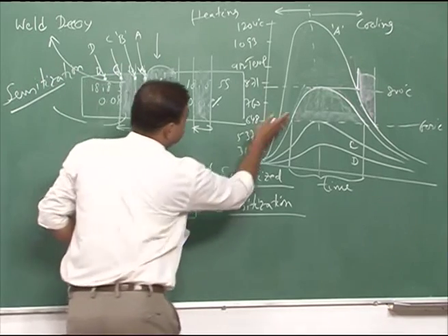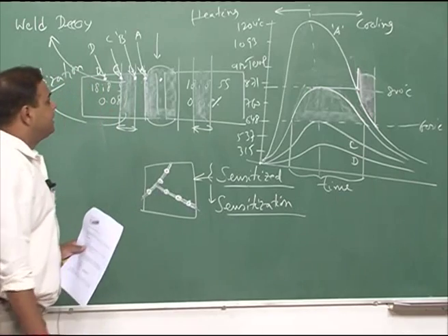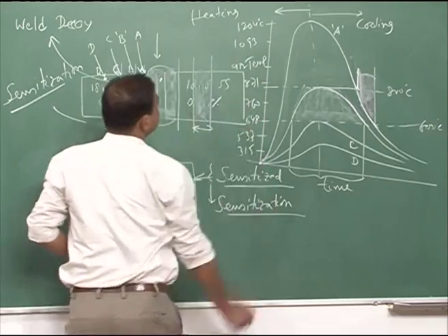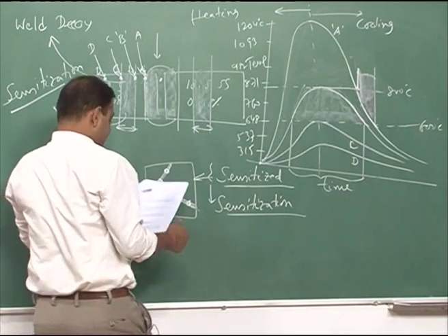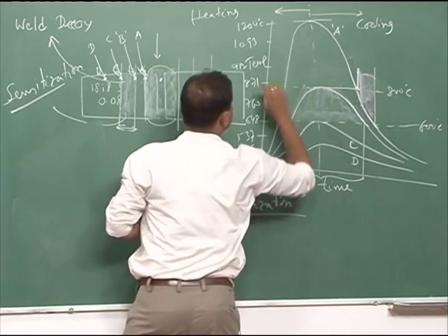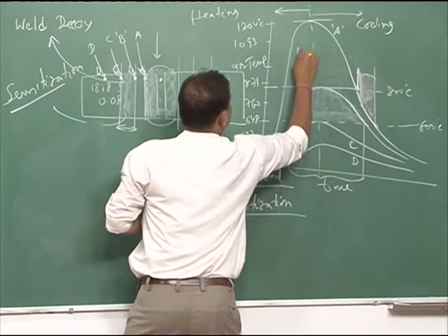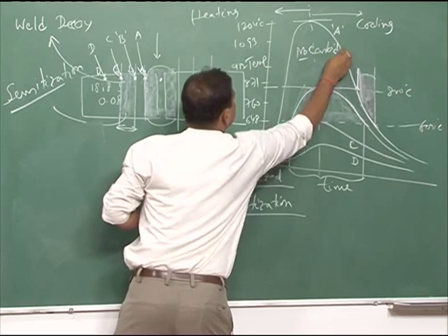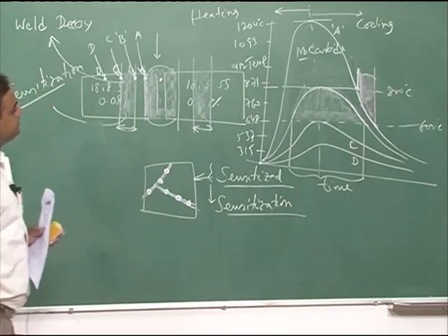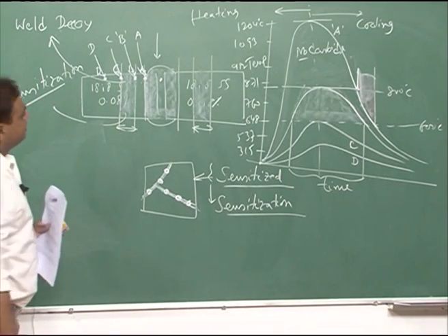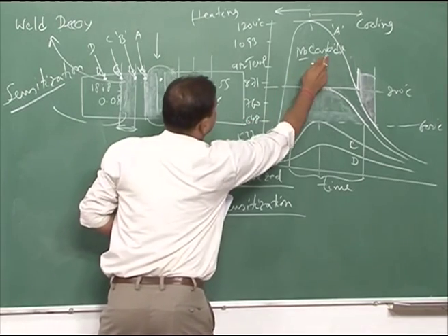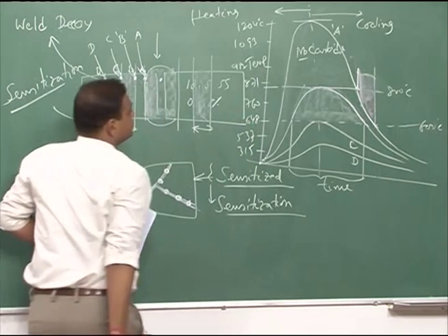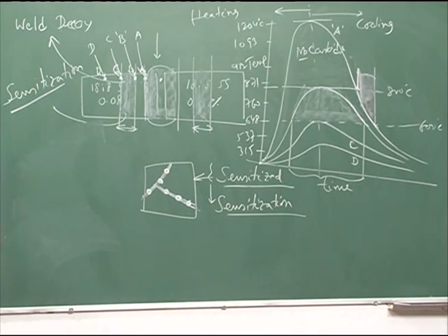Now, if the system has niobium carbide, and then if we heat it like this, up to 1200 this point, niobium carbide will remain as niobium carbide. And beyond this temperature zone, chromium carbide would dissolve if there is any chromium carbide.